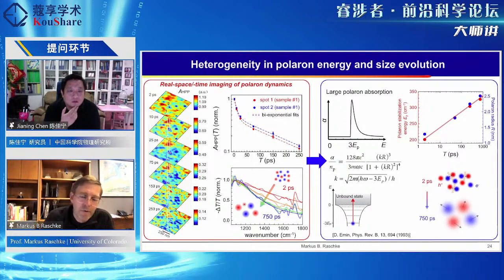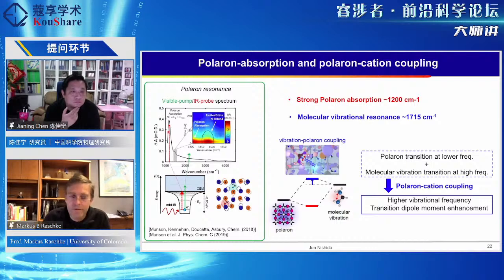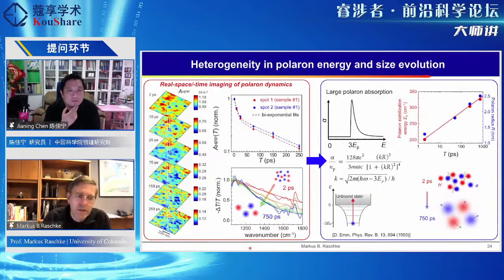Well, whether it's a polaron or a Drude response is actually open. There's this spectral signature that people have observed, which has been attributed to polaron. There's theory which supports this, but there is a growing body of literature now thinking whether this is more a Drude type or a combination response. This is difficult to determine, but in terms of the heterogeneity, it's of course not that we have phonon polaritons, right? That is where you would get the pattern you describe, because then you have propagating phonon polaritons which edge and tip scatter. In this case, the dynamics is determined by the polycrystallinity. And if you look closer at the data, you can see that on different crystallites there are slightly different dynamics.